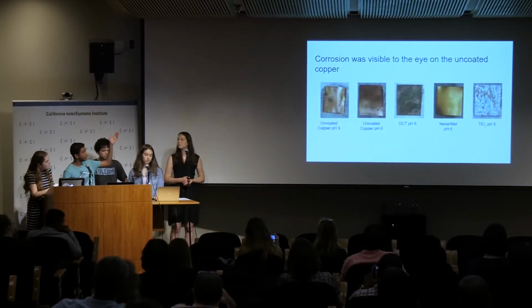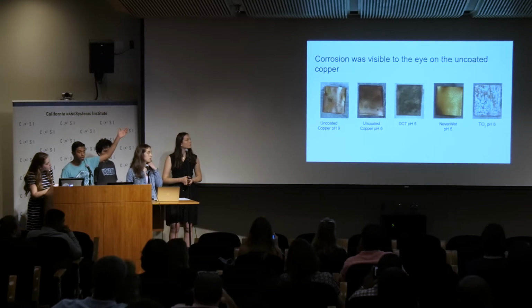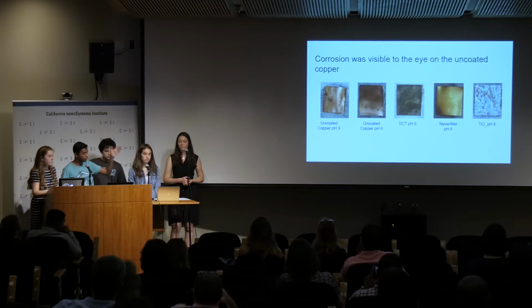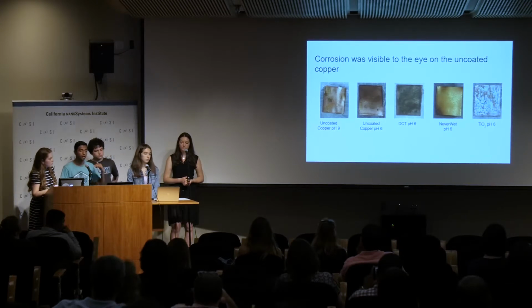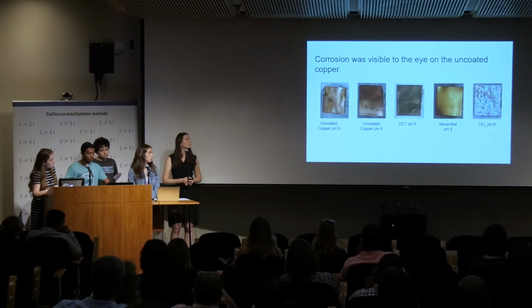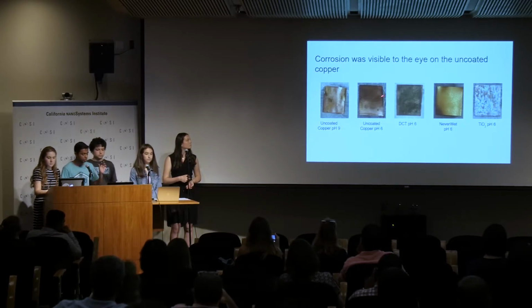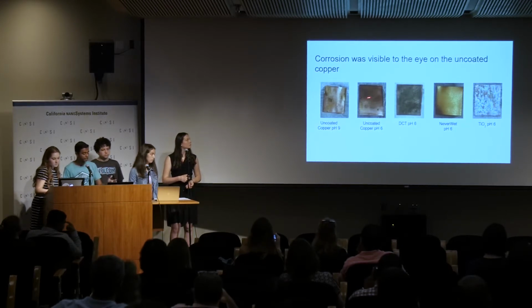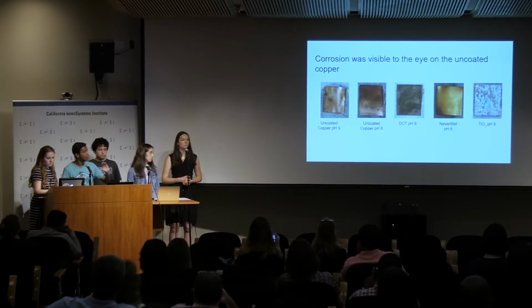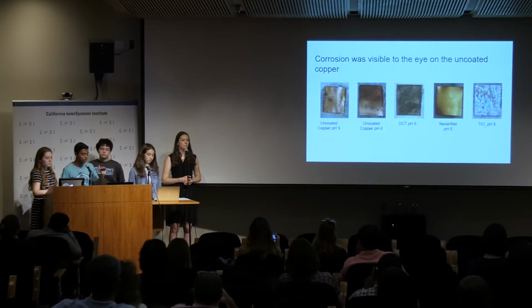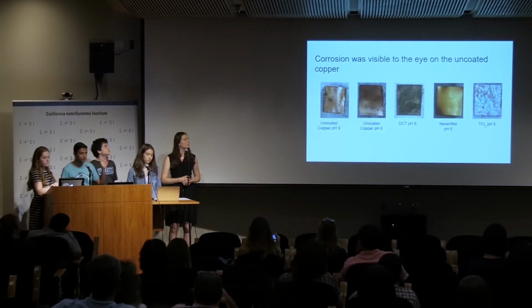And we can see that our uncoated copper in both the pH 9 and the pH 6 solutions have corrosion. As you can see, the shiny copper oxide layer has completely gone. Further, there are darker spots which indicate corrosion as well. The DCT is actually not corroded. That's actually just the silver on the coating. So the metal was more or less unharmed, as we could tell from our mass data, and the Never Wet and the TiO2 also held up pretty well.